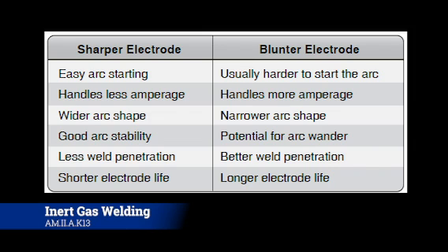Now, this table will show the effect of a sharp versus blunt electrode with transformer-based machines. Effectively, a sharper electrode is easier to arc, doesn't require as much amperage, is wider, has good arc stability, but it does have less weld penetration, and it does have a shorter life. A blunter electrode, on the other hand, is going to be a little bit harder to start and get going, but it does handle more amperage. It's a little bit narrower, but it has the potential to wander. So it's going to require a more skillful, more attentive welder, but it does last longer and have better penetration. So you can make adjustments to the electrodes as needed as you progress on in the job.